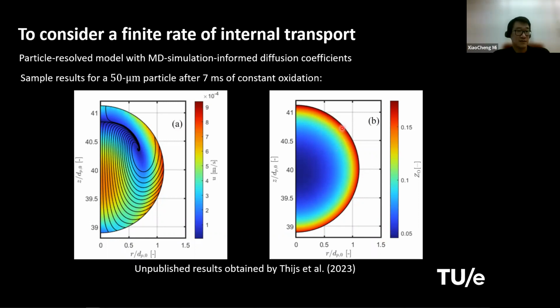So that means that the transport of oxygen inside the particle is not as fast as we assumed before, right? This internal transport might happen over a time scale that is comparable to the entire combustion process, to the other transport processes. So I think this is very likely the right direction that we need to look into.